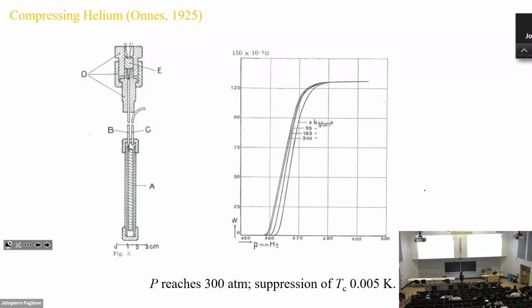So with this setup, they can reach 300 atmosphere. That's actually pretty sizable already. We have a tube furnace, a floating zone tube furnace, for this winter school. We can go probably 10 atmosphere. So at the time, they could reach 300 atmosphere. That's pretty large already. But Tc got suppressed by only this much.